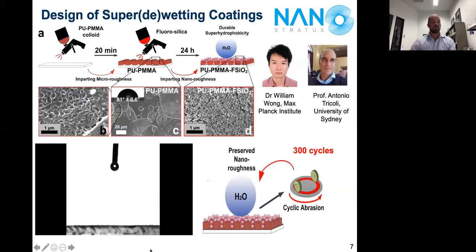And you can see this water droplet dropping down on the surface, and it just bounces and rolls off these surfaces just because of the surface energies that we've created there. And the real advantage of our system compared to any other previous reports globally is that we managed to achieve an ultra durable coating. So we have this abrasion test that you can see here. We run these weighted wheels over the surfaces, and they're basically like sandpaper, and we can go out to above 300 cycles, and any coatings that we tested that have previously been reported in the literature are degrading. This is probably between an 8 and a 10-fold improvement on those coatings.